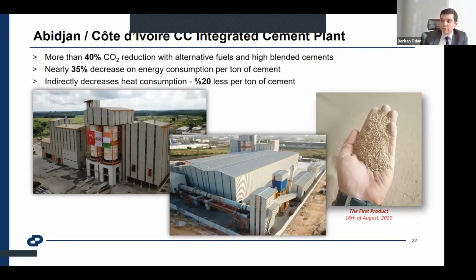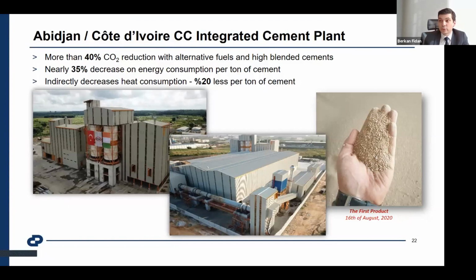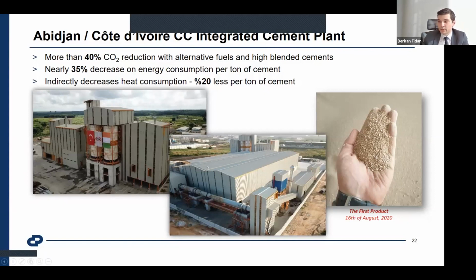Our aim and target is to reach 40% CO2 reduction, with additional fuels and alternative fuel options and high blended cements, and a 30% decrease in energy consumption. There is also an indirect effect on heat consumption due to decreasing clinker amount, and less heat-consuming calcined clay, with 20% less clinker per ton of cement. And you can see the first product. It was in our hands on the 16th of August 2020.